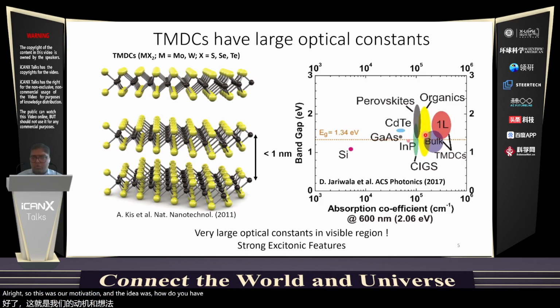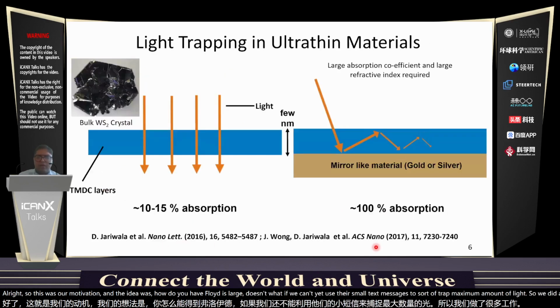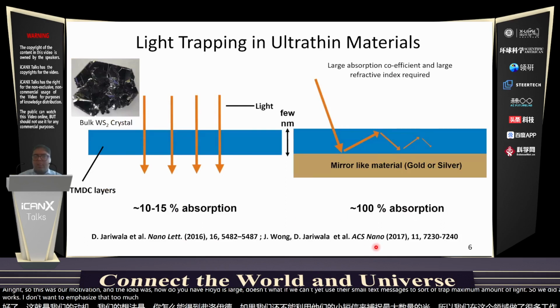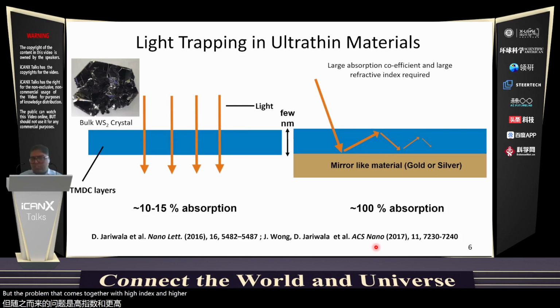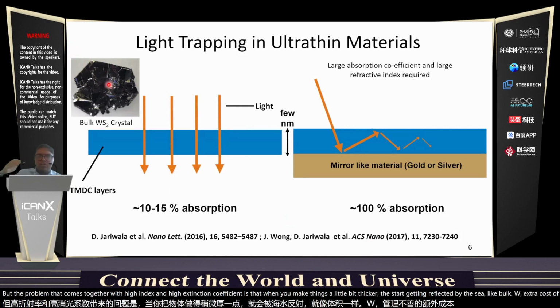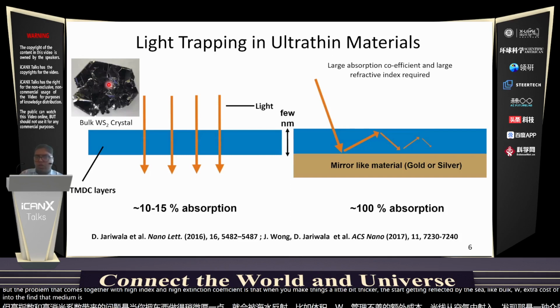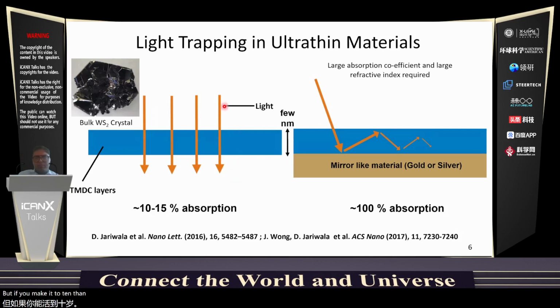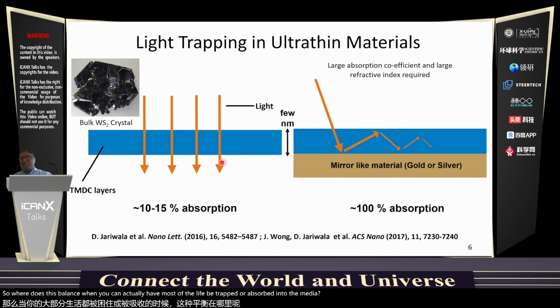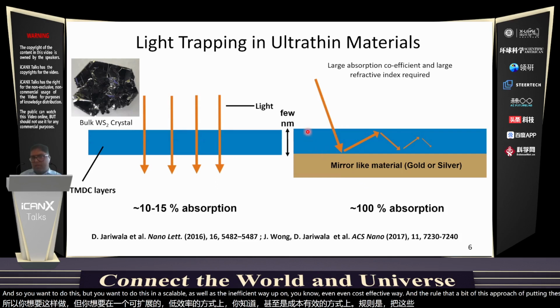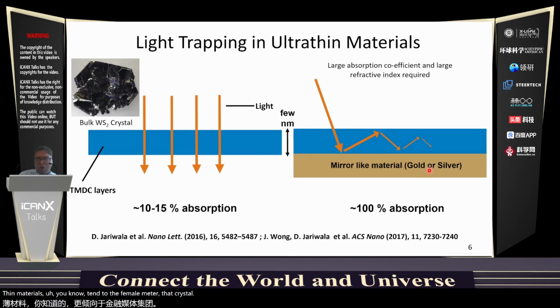The idea was, how do you exploit this large absorption coefficient yet use their small thicknesses to trap the maximum amount of light? We did a lot of work in this area in photovoltaics. This is older work, so I don't want to emphasize it too much. But the problem that comes with high index and high extinction coefficient is that when you make things a little bit thicker, it starts reflecting. If you see a bulk WS2 crystal, the mismatch in refractive index with light coming from air into this high-index medium is so large that most of the light gets reflected. But if you make it too thin, then most of the light gets transmitted. So where is the balance where you can have most of the light be trapped or absorbed in the medium? You want to do this in a scalable, efficient, and cost-effective way. To do that, we took the approach of putting these thin materials, 10 to 15 nanometer thick crystals, onto reflective gold or silver substrates.